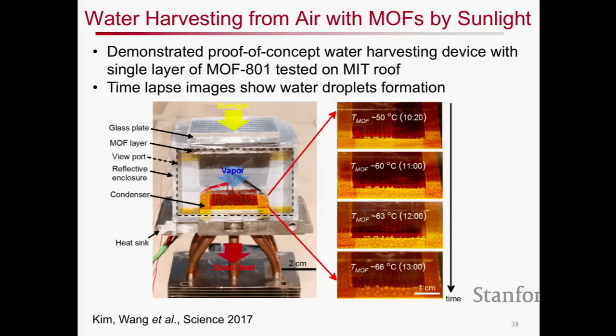What we've done here is incorporate it into this matrix and then have essentially a box that we've designed such that we can shine sunlight with an absorber on it that then heats up this layer. Once it's captured enough water vapor, or saturated in this case, you can release it, and you can see that in fact you're condensing water in this case, and you can eventually collect that.